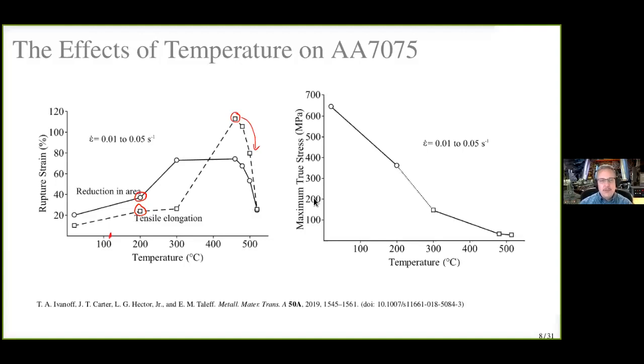But another effect you get going to the warm temperatures is a drop in the flow stress by about a third. Why do we care about that? Well, when we're doing a stamping operation, we have something called spring back. Think about your stress strain curve. Whenever you load something to plastic deformation, you always go through the elastic deformation first. That elastic deformation is held in the material, and as soon as the dies release, that elastic deformation will recover and the part will spring back.